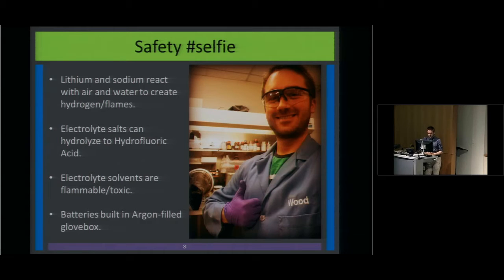Lithium and sodium, which we also do a little bit of sodium-ion battery work with, are both materials that degrade when they come in contact with air. If they come in contact with water, they give off hydrogen and sometimes fire. The electrolyte salts we use in the batteries can hydrolyze to form hydrofluoric acid, which is not only a really strong acid, but it literally leaches the calcium out of your bones, causing a pretty horrific death. The electrolyte solvents we use are also flammable and toxic, not fun to breathe in.